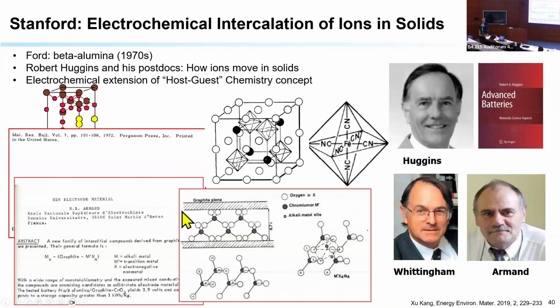So this intercalation of the lithium inside a solid is really the basis of a charge and discharge of the lithium ion battery. You intercalate, you charge, you de-intercalate in the anode, and then you discharge. So understanding this science of intercalation, de-intercalation, the nature of the chemical bond when you have the intercalation, at what voltages, what electrolyte, was a very critical concept. So the SEI layer formation, number one, the intercalation, de-intercalation chemistry and physics, number two, were fundamental to the discovery or the realization of the lithium-ion battery that we use today.